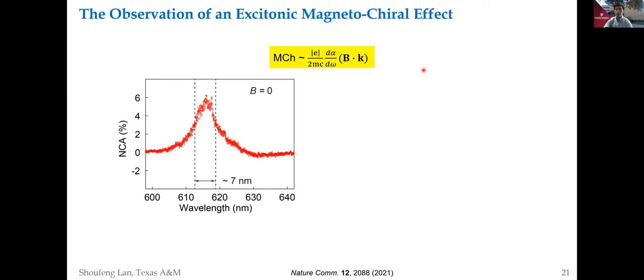For the chirality, we obtain the natural circular anisotropy, or NCA, by subtracting the LCP and RCP components of the emission. We can see a gigantic peak at the wavelength of 615 nanometers, which means that this chirality is strongly enhanced by the plasmonic effect. And the spectrum width is around 7 nanometers.